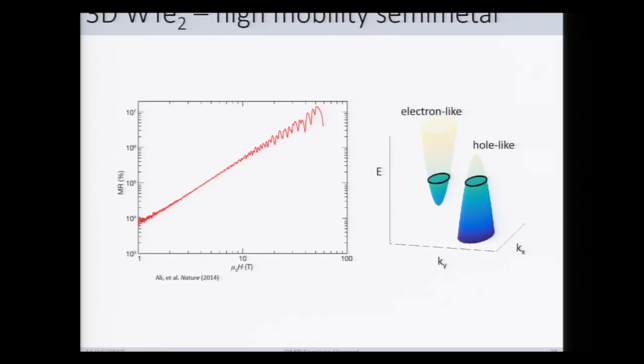Another nice aspect about the bulk crystals is that it's a high mobility semi-metal. And you know, the semi-metal part maybe is tangential, but the fact that it's high mobility is important. Even in the first bulk crystals grown in the Cava lab, the magnetoresistance, this is the magnetoresistance in percent on the log-log plot as a function of magnetic field, is in excess of 10 to the 7 percent, so a relative factor of 10 to the 5 at these high magnetic fields.